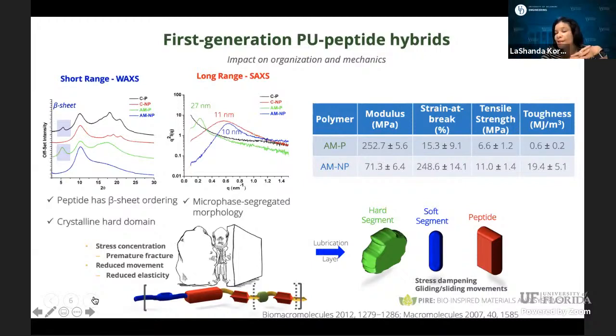Now, how does that translate to mechanical properties? Because we started out thinking about how hierarchy influences mechanical properties. If you draw the comparison between just our amorphous hard segment and whether it has a peptide or not, you can see that the inclusion of a peptide actually gives you a much higher modulus than its AM-NP control. But you have a substantial decrease in the overall extensibility of these systems, which then leads to a lower toughness. And we believe this is because of stress concentrations.